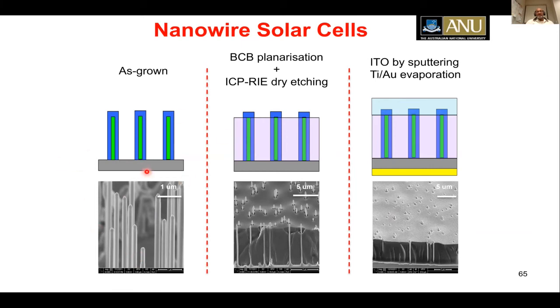And then to make contacts, you fill the gap between the nanowires with a polymer material. You selectively etch that using plasma etching and make some indium tin oxide contacts at the top and the metal contact at the bottom. And then you shine the light and measure the IV characteristics of these particular solar cells.